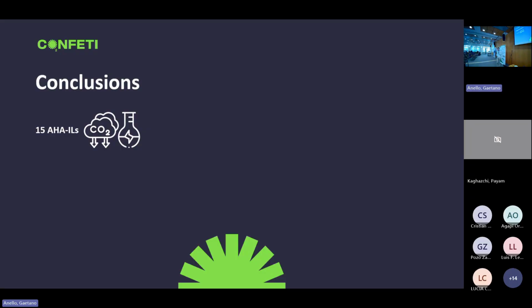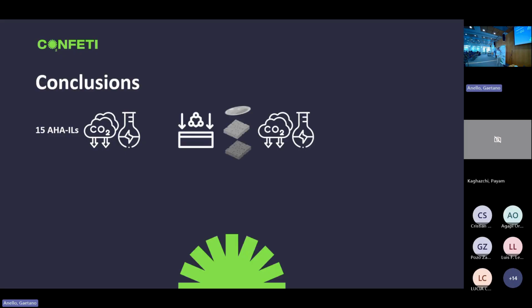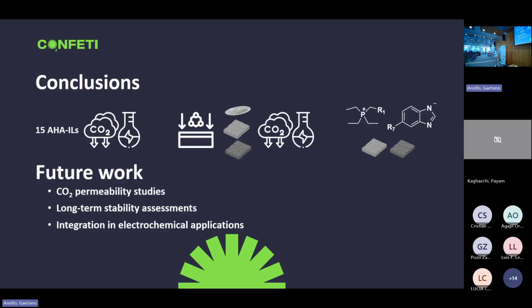So as a conclusion, we developed and synthesized 15 ionic liquids. We tested the capture capacity and the electrochemical behavior, properties. Then we immobilized them in 3 different solid supports, obtaining 2 different materials with 1 ionic liquid with high capture capacity in these DAC conditions. So now as future work, we want to study the permeability of these materials, the CO2 permeability, the long-term stability, and finally the possible integration in some electrochemical applications.